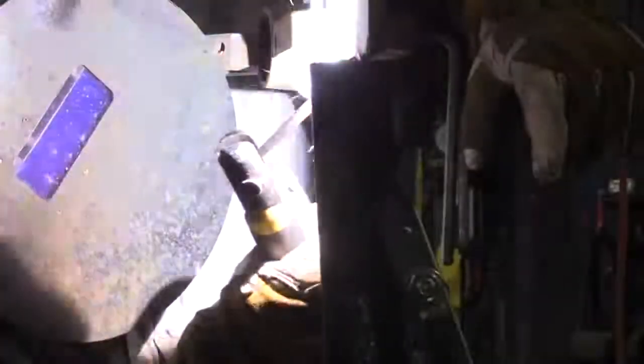Okay, almost done with the first pass. Not really experiencing any arc blow, and part of that is because we do have the amperage set down toward the lower end of the range with the arc force set at about 50%, which is a little bit higher than recommended for 7018, but it's working out. Andrew likes to weld them all the way to the end and then wrap the corner.